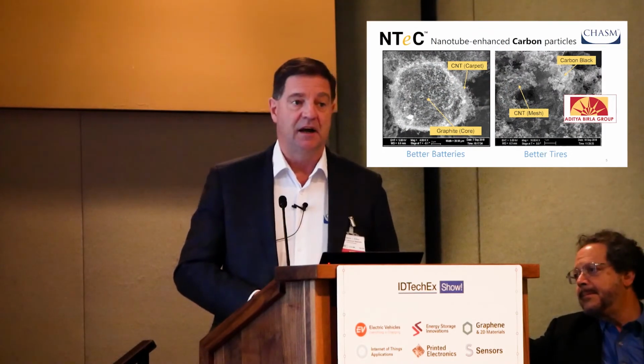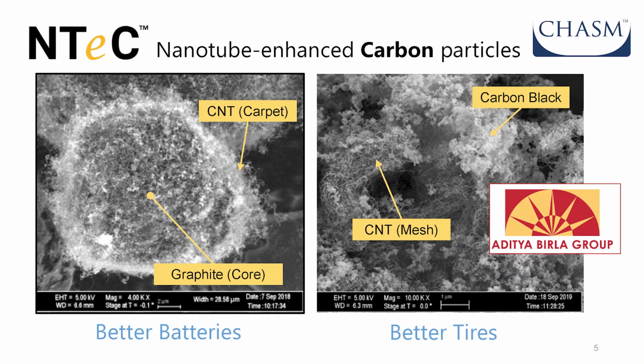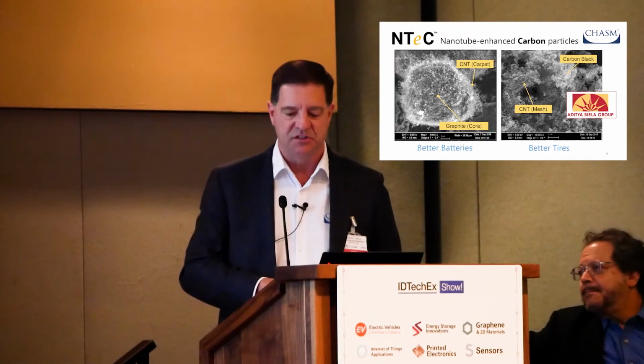Just really briefly, this material, NTeC, nanotube enhanced carbon, is a really cool material. It's not the subject of my talk, but this is an example of a graphite core particle that is carpeted with carbon nanotubes. In this material, graphite is normally used as an anode material for lithium-ion batteries, and this will result in better batteries if the graphite is upgraded to this material. Another version of NTeC is a carbon nanotube mesh encapsulated carbon black. So you have an enhanced carbon black material. Carbon black material is used extensively in tires. We expect this will allow tires to get the unattainable triad of long wear life, great traction, and low rolling resistance. We recently announced a strategic alliance with Birla Carbon to accelerate the development and commercialization of those materials.